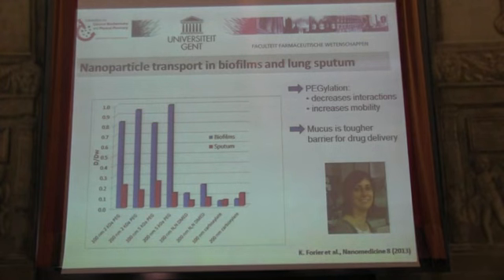So after quantification, we see that clearly. These are the pegylated, the first four. Pegylation clearly improves mobility. And it also shows that it's not the biofilm that is the hardest barrier, it's more the sputum, the sticky mucus, that is more difficult to penetrate, with lower mobility. And charges should be avoided. That's what we learned from this.